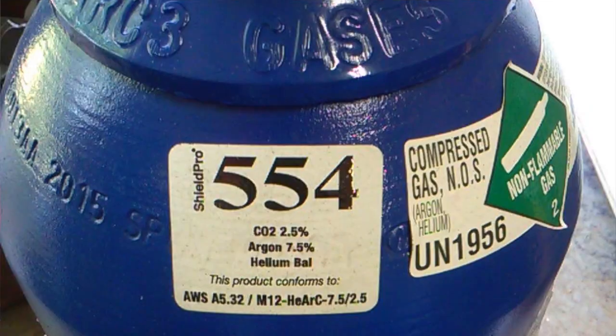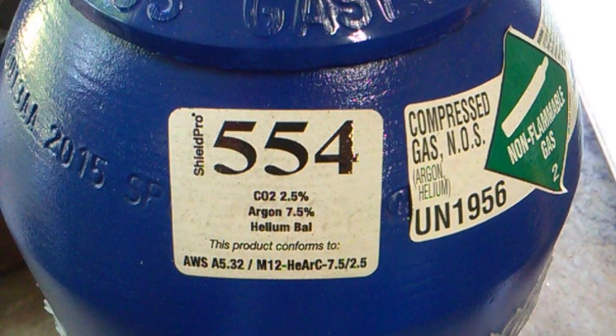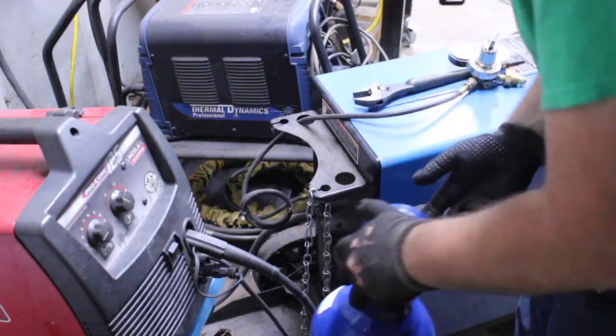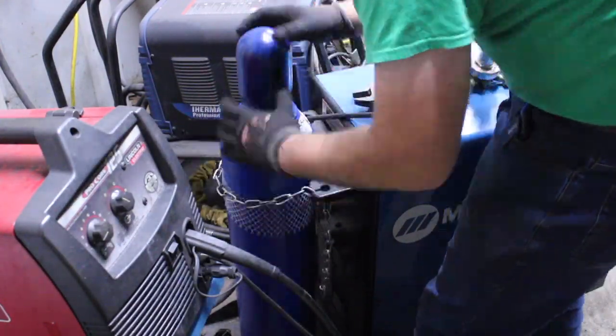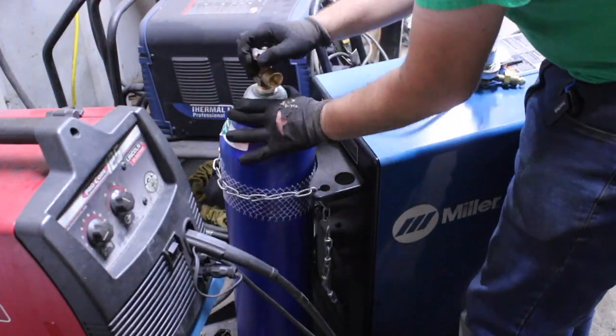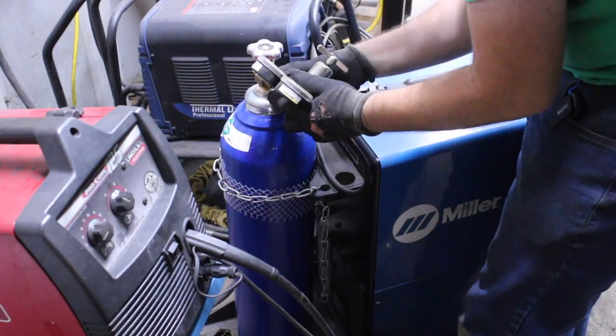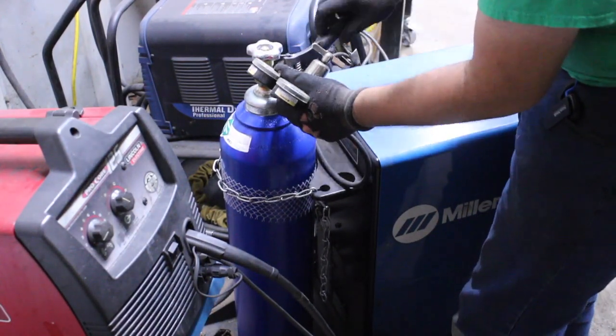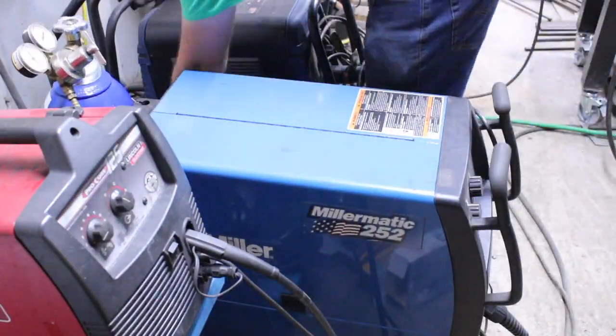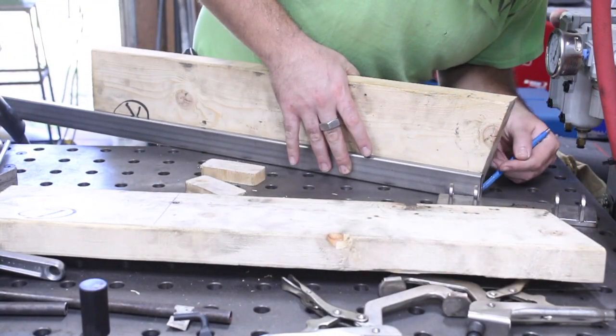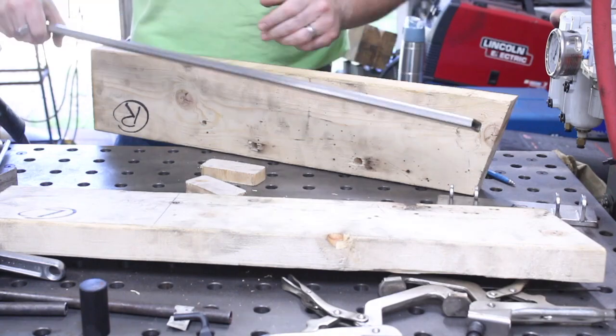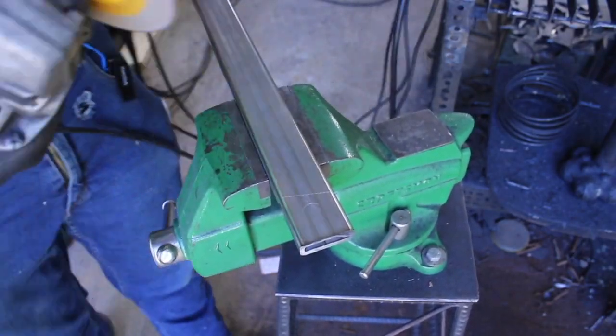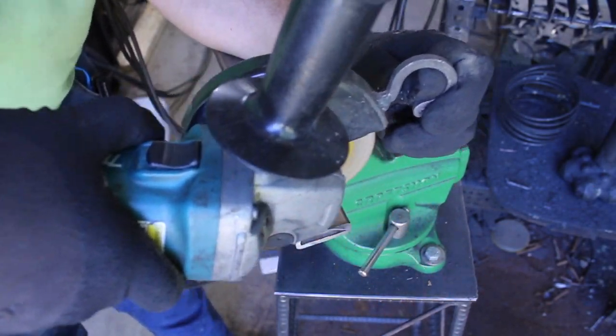That is Shield Pro 554. That's 90% helium, 7.5% argon, and 2.5% CO2. And that I found to be the most effective for stainless steel, especially for near spray. We're very high up in the range because I tend to go pretty quick on stainless steel because of that thermal conductivity.